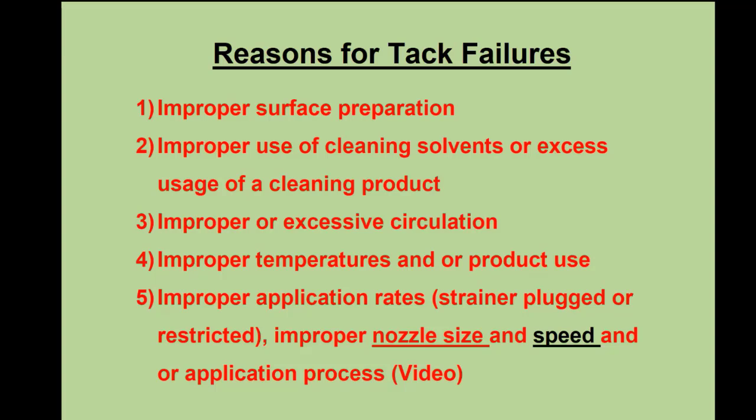Improper circulation or excessive circulation will break down an emulsion. Emulsions are nothing more than oil suspended in water and coated with an emulsifying agent to keep it there. It has a shelf life, and improper temperatures or improper circulation will affect that.